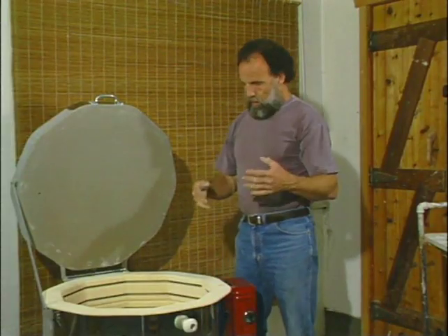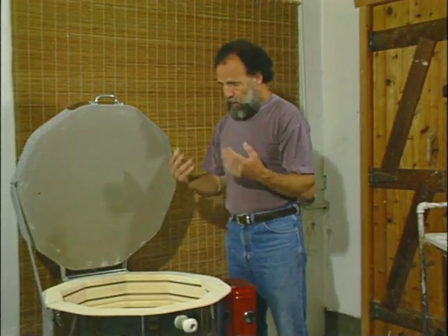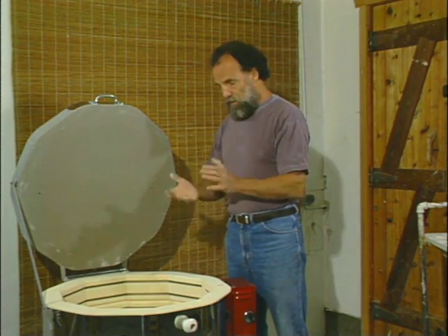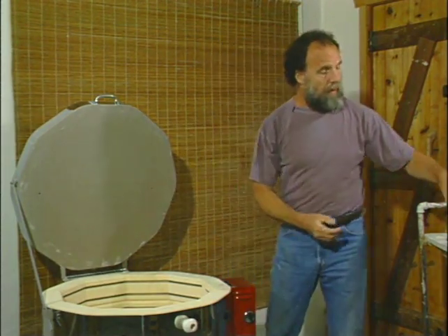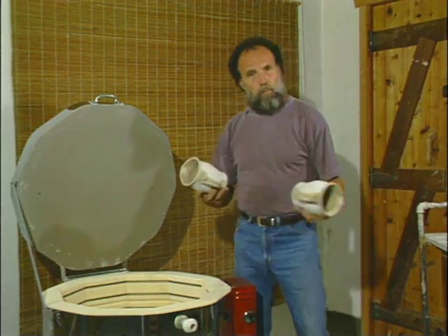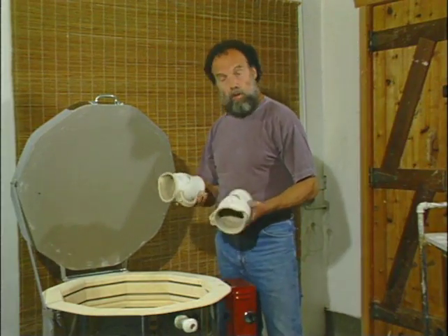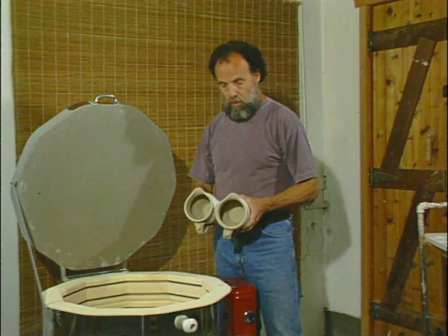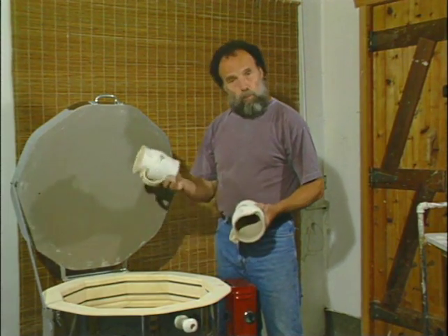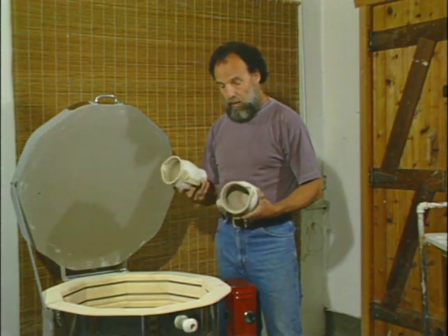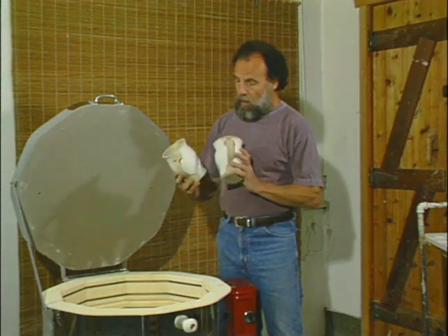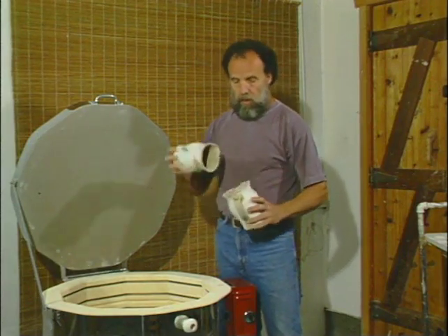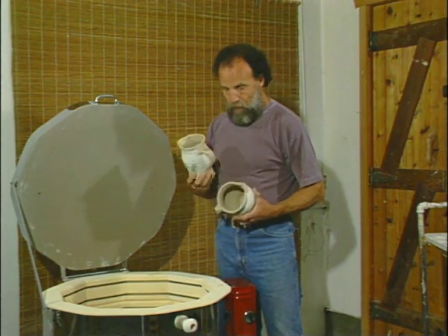With a bisque firing, what you're really interested in is getting as many pots in as possible. And it's quite okay in a bisque firing to allow the pots to touch one another. There is no glaze on the pot, and there's no reason why they'll stick together. The slips that we've used to decorate, of course, are not tacky at bisque temperatures, so we'll be able to allow the pots to touch one another, and indeed we'll be able to stack pots up.